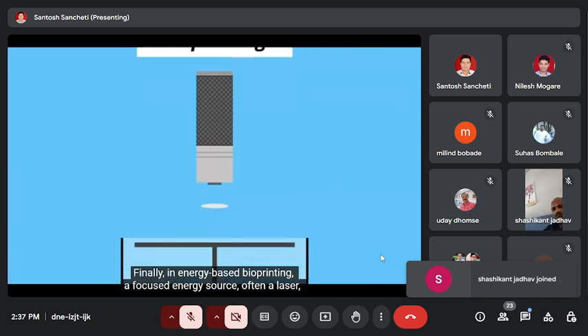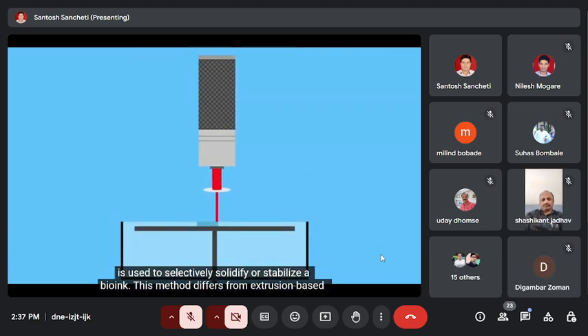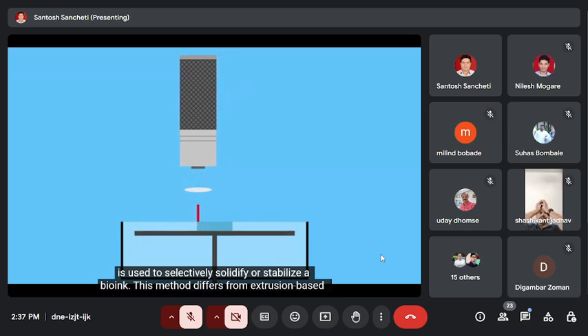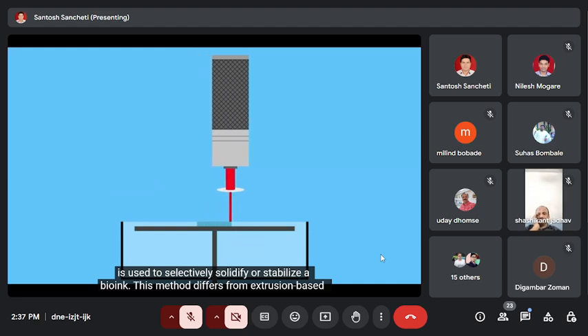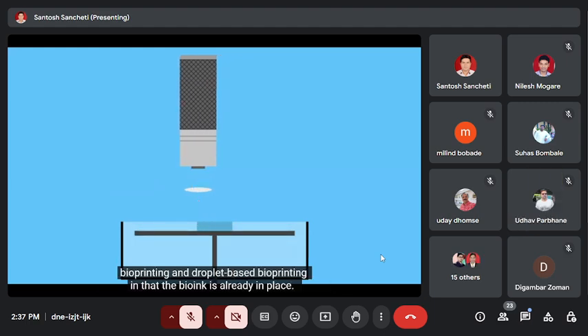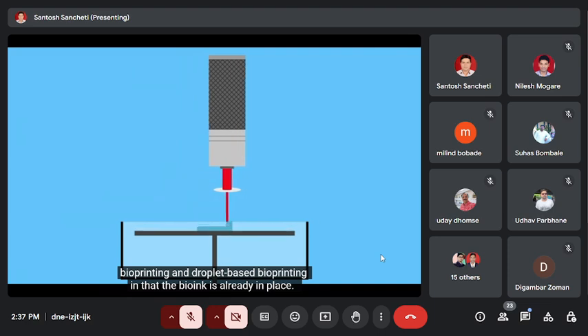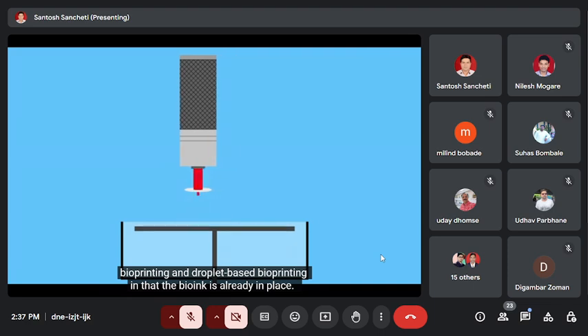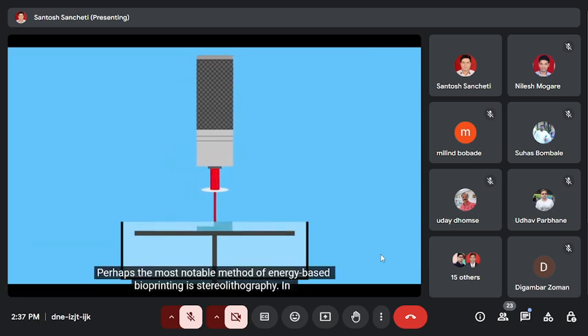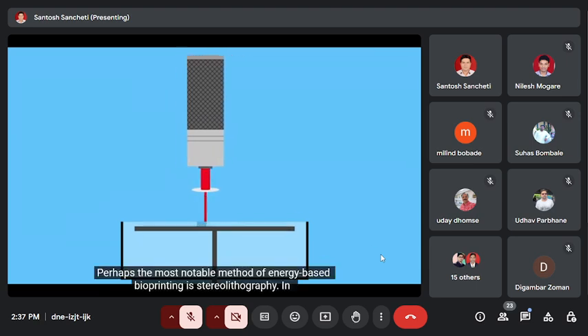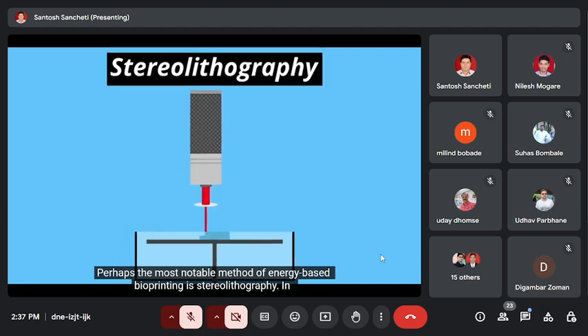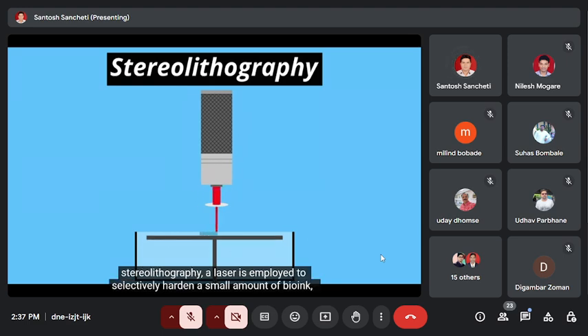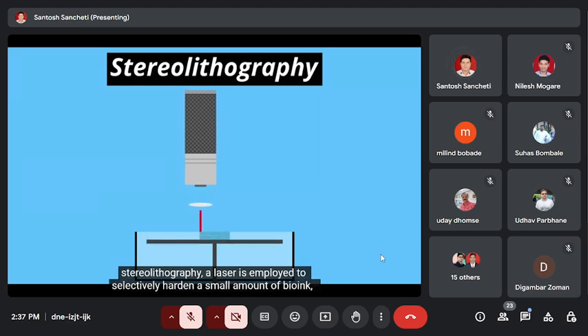Finally, in energy-based bioprinting, a focused energy source, often a laser, is used to selectively solidify or stabilize a bioink. This method differs from extrusion-based bioprinting and droplet-based bioprinting in that the bioink is already in place. Perhaps the most notable method of energy-based bioprinting is stereolithography. In stereolithography, a laser is employed to selectively harden a small amount of bioink, which contains a light-sensitive hydrogel.